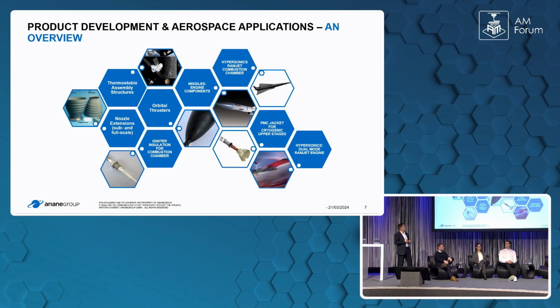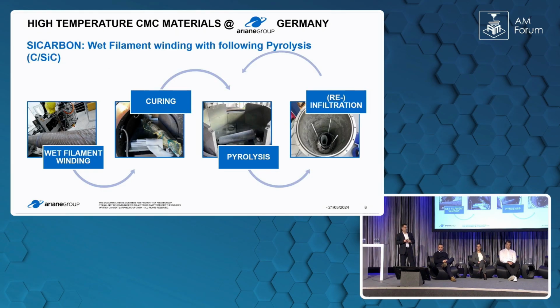We work on thermostable assembly structures with a CTE close to 0 in a big temperature range. We work on orbital thrusters, missiles, because technology for small missiles, for propulsion systems, is quite similar to technology for a big launcher. And our main work at the moment is work on hypersonics for defense application, in the field of propulsion, in the field of structural parts, and so on. We work only, or more or less only, with black CMCs, meaning non-oxide CMCs.